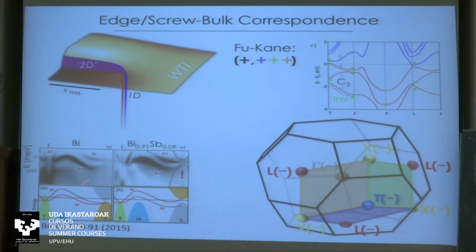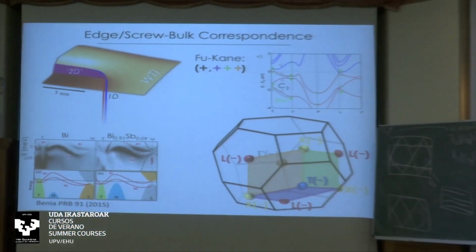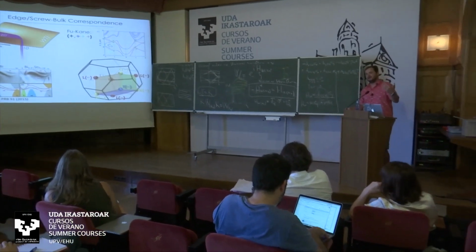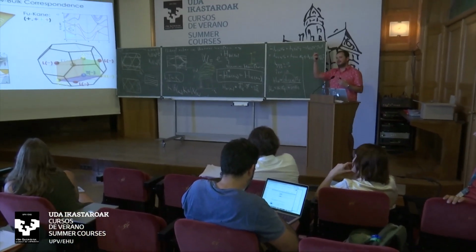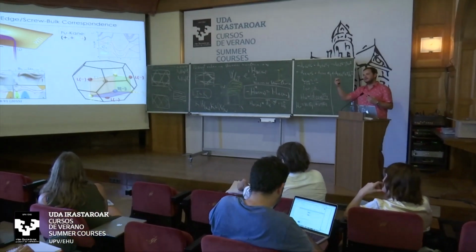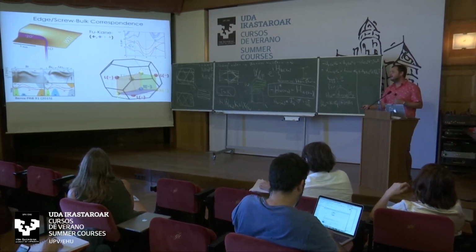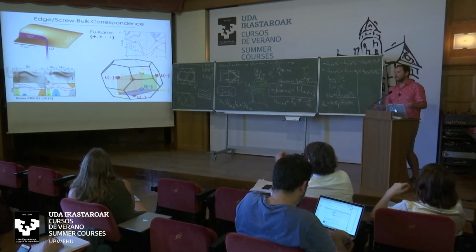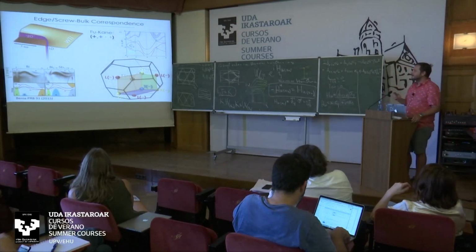The possible reason that the bands themselves are not apparent is because a small gap comes with a very large penetration depth. So probably what happens here is that as you approach the L point, or the surface projection of it, which is the M point, the penetration depth of these surface bands grows, almost diverges, and this is why we lose visibility as we approach this point.